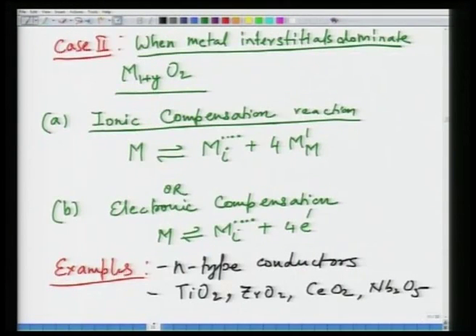And then we looked at the case when metal interstitials dominate. In that case, the formula would be, for example, in this case, we have taken MO2. So here it would be M1+YO2. And as a result, since metal is +4, we can see the metal will form an interstitial, complemented by reduction of metal on the metal site, or if it was electronic compensation, then it would give rise to 4 electrons. So the difference in two cases is the number of electrons created, the relative proportion of two defects. And examples of such cases could be n-type conductors, materials such as TiO2, zirconium oxide, cerium oxide, Nb2O5.